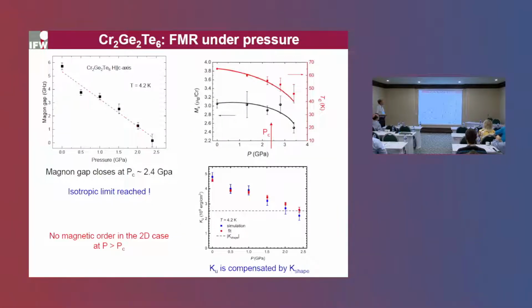So it turns out that with pressure, we can close the magnon gap. So we get an isotropic limit. Of course, that was a question: what is the reason for that? It might be that with the pressure, we simply suppress ferromagnetic order, or reduce the magnetization.